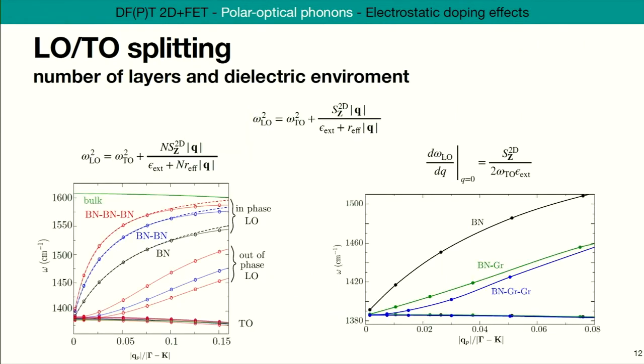Okay, so let's go a little bit deeper into what happens here. Looking at the analytical formula, we can ask what happens when you add several layers on top. This is interesting because it gives you the transition between the 2D material and the 3D counterpart, the bulk. So this is what we did here with boron nitride, with one layer, two layers, three layers, and see how it goes. If you look at the analytical formula and try to figure out where the number of layers comes in, it comes in as a prefactor of this parameter here. And this effectively dictates the slope of the dispersion at zero momentum. So the slope increases with the number of layers.